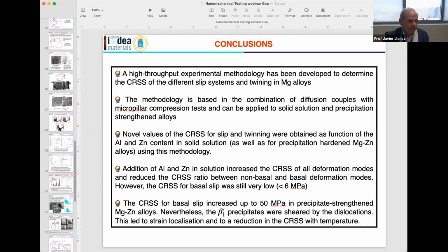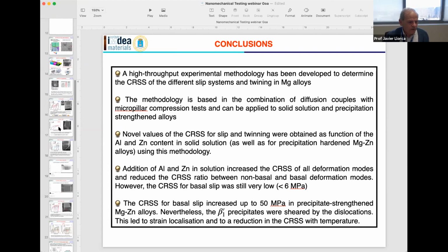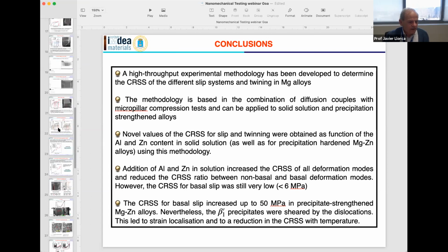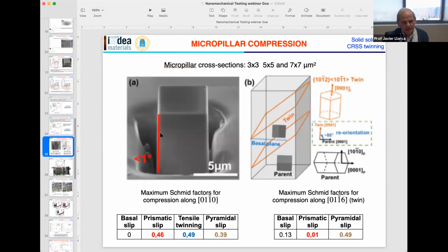When you manufacture pillars with a square cross-section, it's much easier to reduce the taper, because you can rotate the micropillar and reduce the taper on each one of the surfaces. So there's one reason: tapering is reduced.